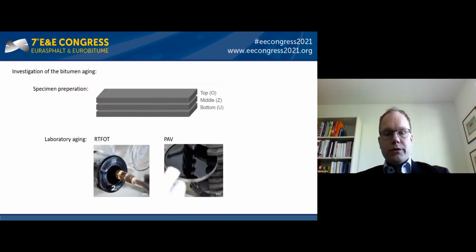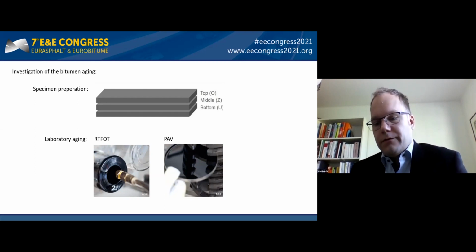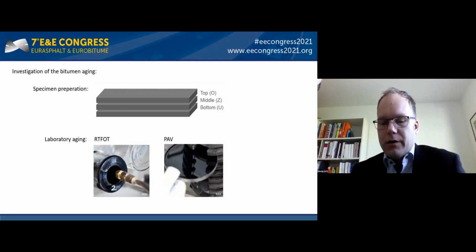The binder aging was investigated for three layers of the specimens. The specimens were cut into a top, middle, and bottom layer to see if the heating is affecting one layer more than another. As reference, RTFOT and PAV tests were carried out. As binder investigation methods, the softening point was used and FTIR infrared spectroscopy was used, and there the A1700 method after the Belgium Road Research Center was used.